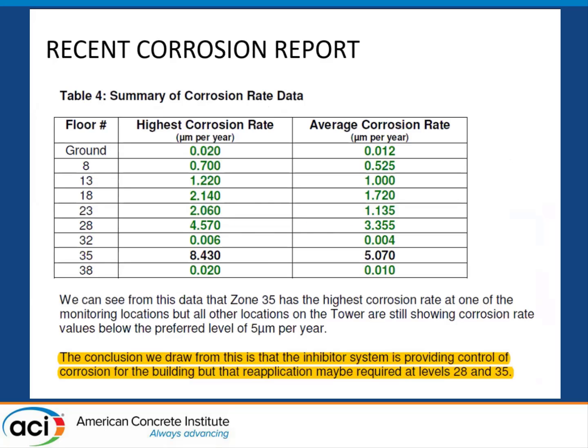A report by the corrosion engineer was recently supplied, looking at all of that corrosion data, and their conclusion was that the point on the 35th floor should maybe be looked at for potential reapplication of inhibitor or coating to provide some protection. But take a look at that. There is no spalling, no crack, no rusting. That's the beauty of the monitoring: it allows you to intervene long before you start seeing those other signs.